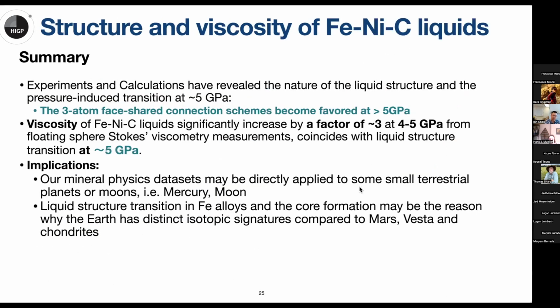So in summary, we found there is a structure transition in iron nickel carbon liquid at around 5 GPa. This has a substantial effect on the viscosity of those liquids at high pressure. The viscosity would increase after the phase transition.